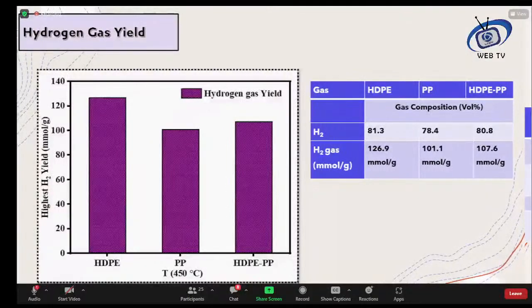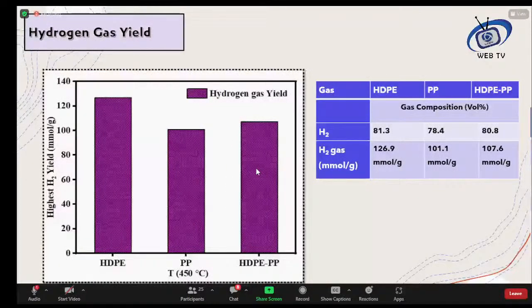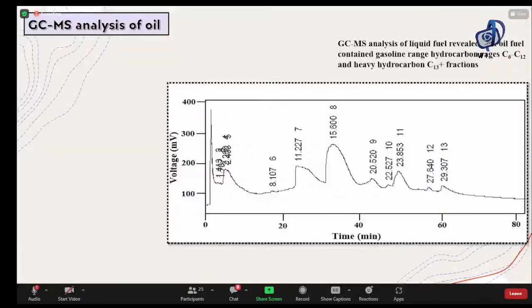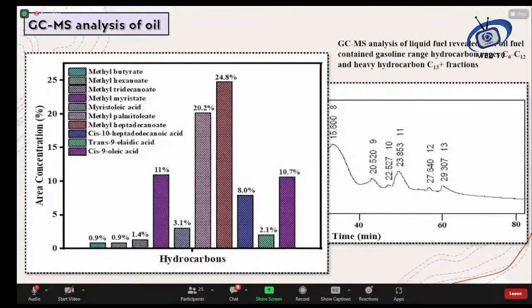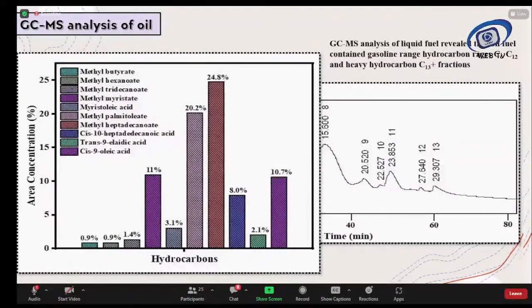Then we conducted the GCMS analysis of the liquid product to check what carbon chains are present in the product, and after that we found that the liquid product contained gasoline range hydrocarbons ranging from carbon 6 to carbon 12 chain, and some heavy carbons having carbon chain 13 and higher. So these are the different compounds we find through GCMS analysis in the product.